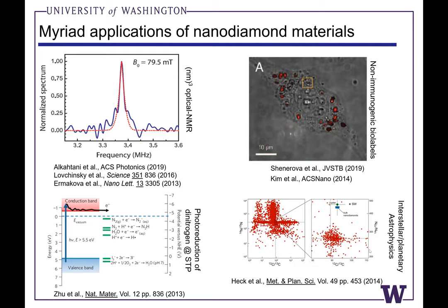And also in terms of basic science, basic research, there are some really beautiful papers using NanoSIMS, secondary ion mass spectrometry, to look at the carbon-13 to carbon-12 ratio in astrophysical diamond materials, nanodiamonds. And you could fingerprint the origin of nanodiamonds following meteoric impacts in space, effectively using this carbon-13 to carbon-12 or nitrogen-14 to nitrogen-15 ratio. So by understanding the distribution of point defects, not just compositional, but isotopic, you can learn a lot about the history and origin of materials in the solar system.